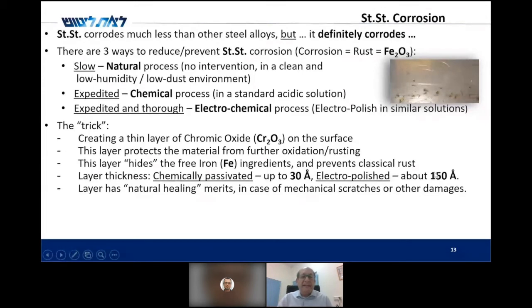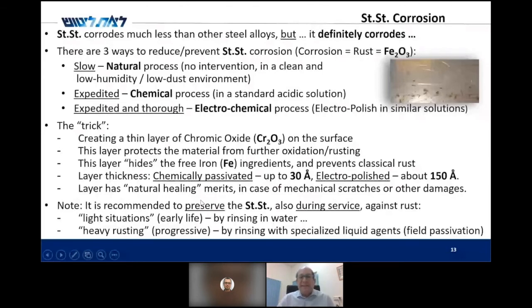This layer has a natural healing merit in case of mechanical scratches and other damages, because it will start growing with the environment oxygen again and make this protection available again. Now, it is recommended to preserve the stainless steel during service against rust in light situations, early life, just by rinsing in water. In heavy, progressive rusting, rinse with specialized liquid agents. This is called field passivation, and I will touch one of the applications like this later on.